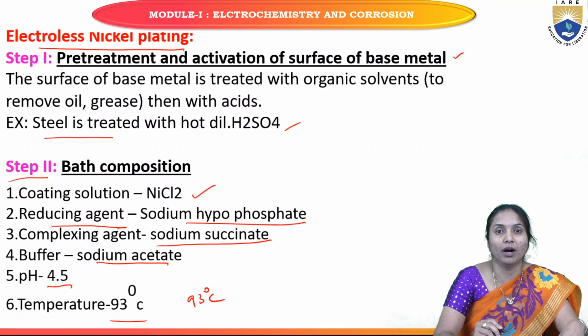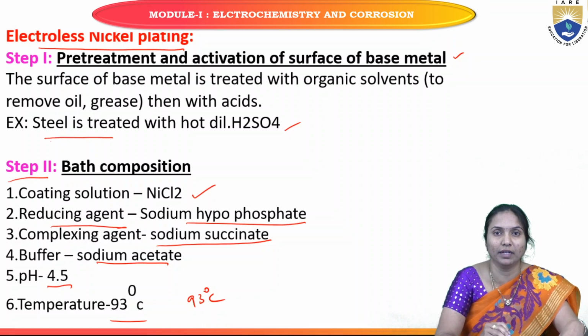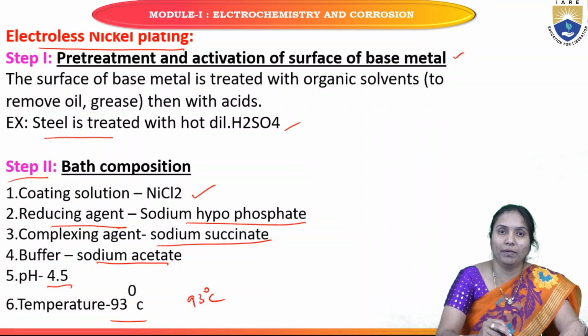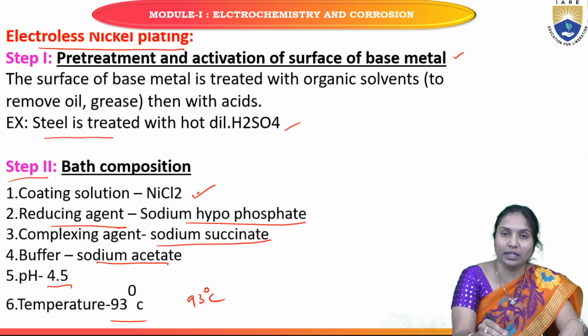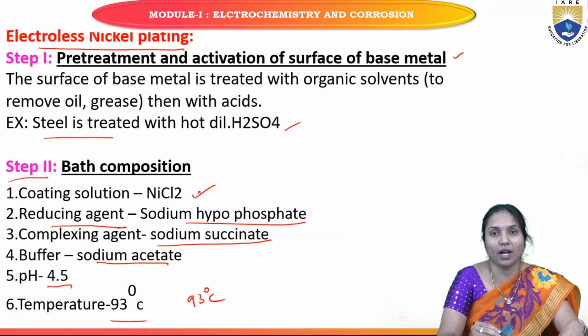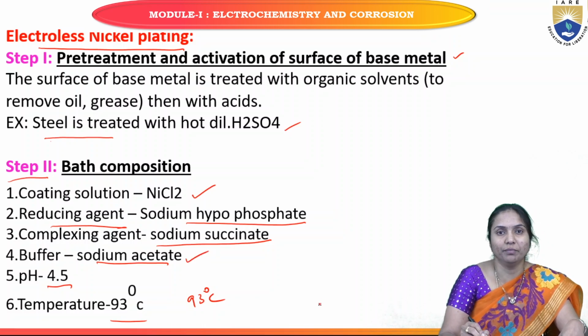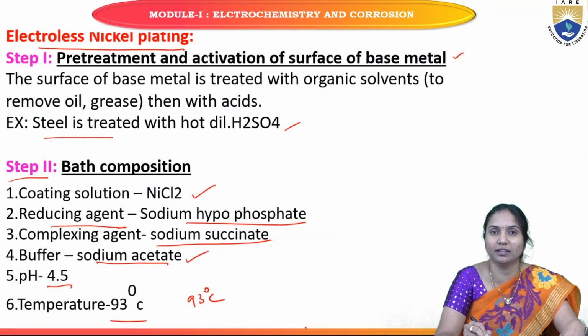The next step, step 2, is the coating bath preparation. In this coating bath preparation, we add the coating metal, the reducing agent, the complexing agent, and the buffer solution also. For example, in electroless nickel plating, we apply nickel coating. The coating material is nickel chloride, the reducing agent is sodium hypophosphate, the complexing agent is sodium succinate, and the buffer is sodium acetate, maintaining a temperature of 93 degrees centigrade and a pH of 4.5.